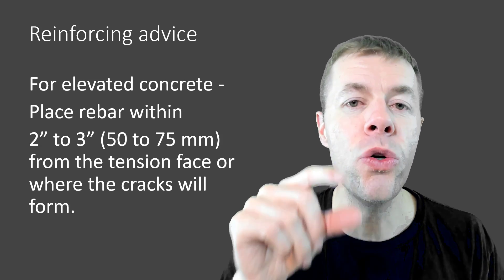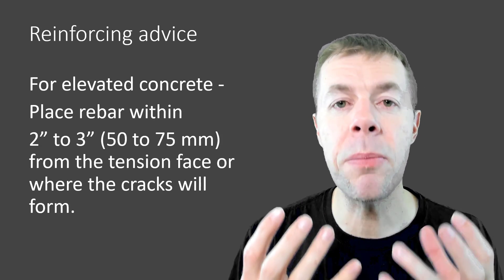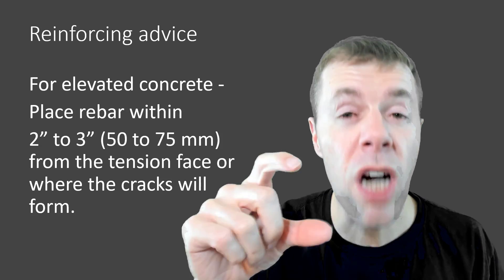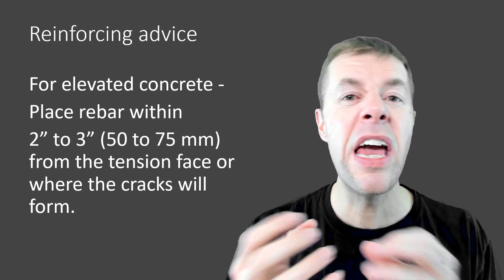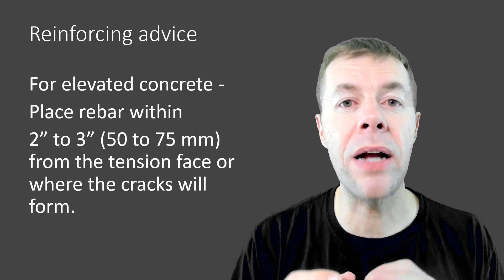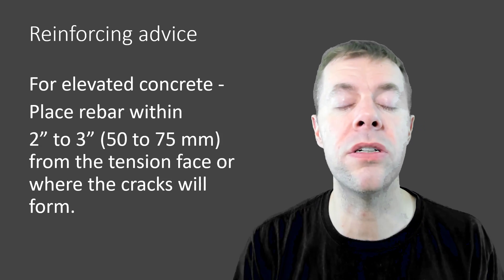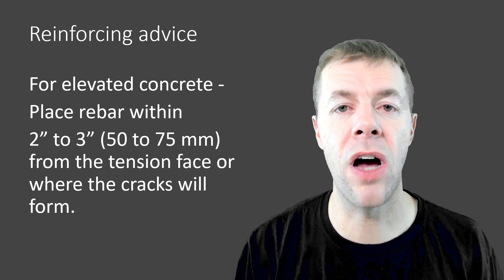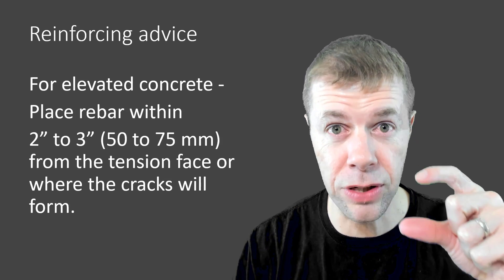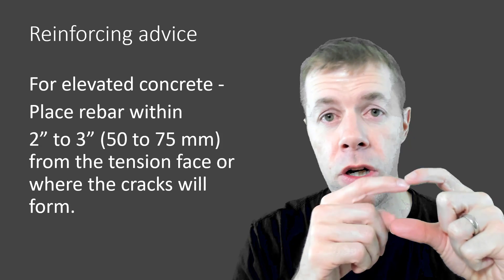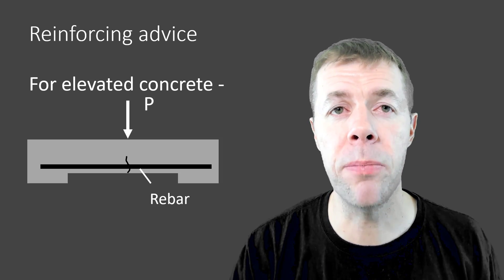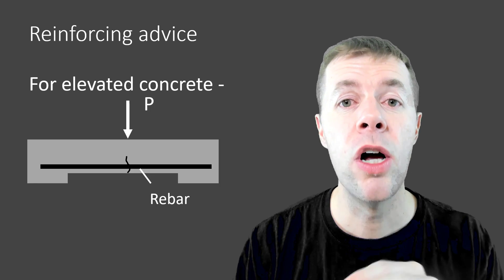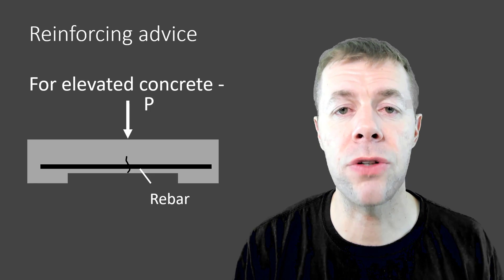You want the rebar between two to three inches of cover. If you're in an extreme environment where you're going to get lots of de-icing salts, you want more cover at about three inches. If you don't expect a lot of de-icing salts, then two inches is a typical number that most people use in their designs — that's the cover between the surface of the concrete and the surface of the rebar. Here's a picture of an elevated slab showing where we want to put that rebar close to where we expect to see those cracks occur.